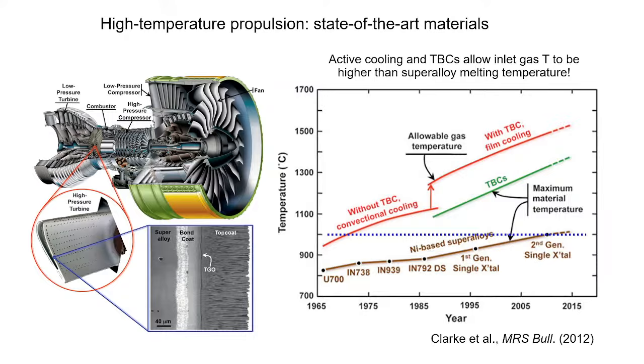So with the combination of thermal barrier coatings and the film cooling from the active cooling, the inlet temperature of the gas coming out of the combustion chamber that's hitting the first high pressure turbine blades is above the melting point of the metal, right? So it's quite dramatic what the improvements have been.